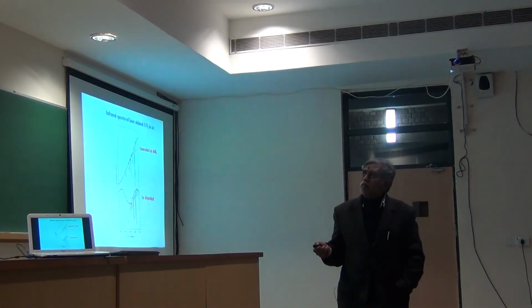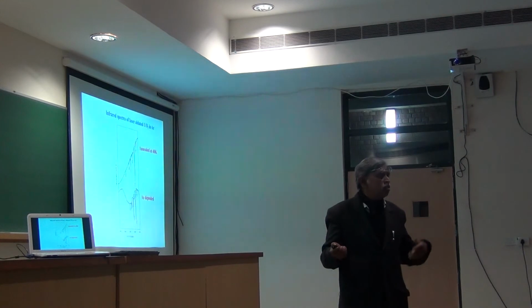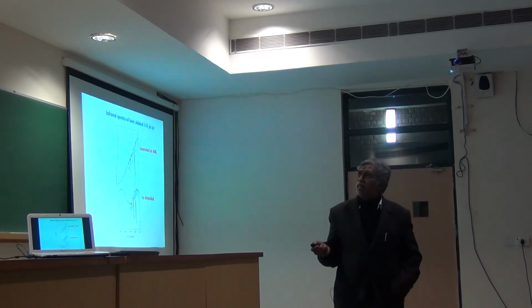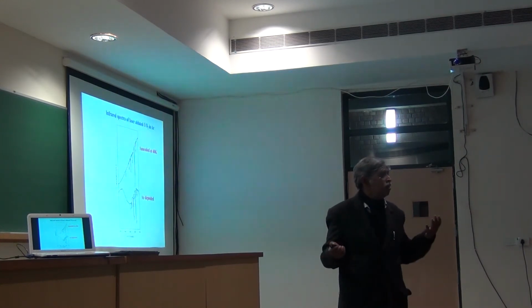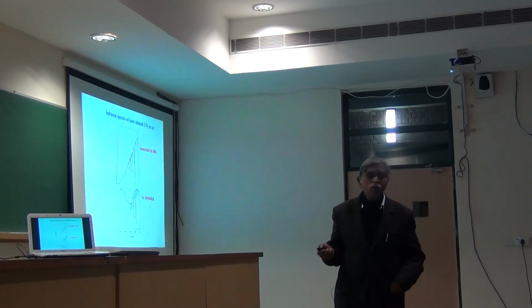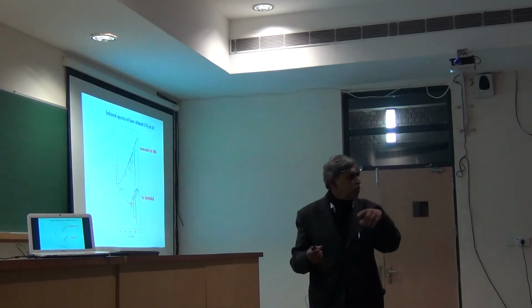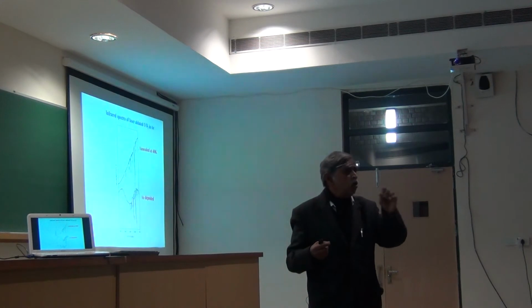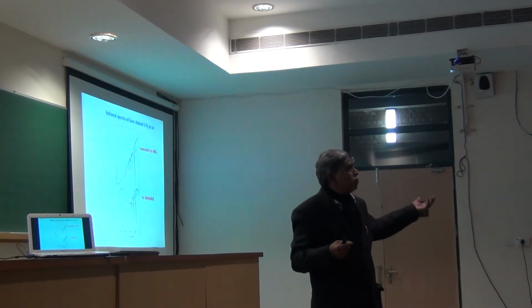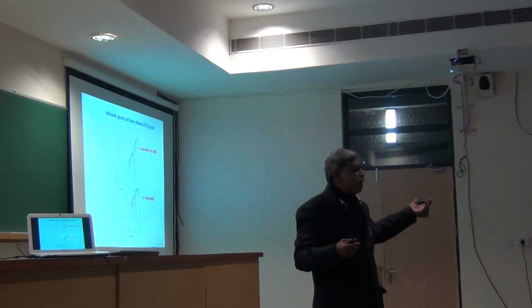But of course, having worked in a nuclear industry, we had to justify our existence over there, and therefore we said, let's study uranium oxide and see what we can get out of it. So we took uranium oxide material and we kept that as a substrate. We hit the laser onto the uranium oxide, and whatever came off, we trapped it in argon. And we said, let's see what we get.